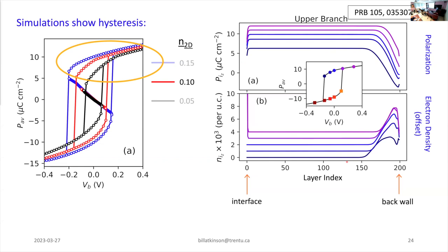So you mentioned that these wiggles close to the back wall in the electron density, I think you suggested they're due to some bands that form. So they're subband quantization, near the wall. Specifically the wiggle in the blue curve on the bottom, right next to the wall. That is a low energy band with DXY symmetry. That band is massive along the Z direction, but light in the XY plane. I see. So it's tightly confined to within three or four layers of the back wall.